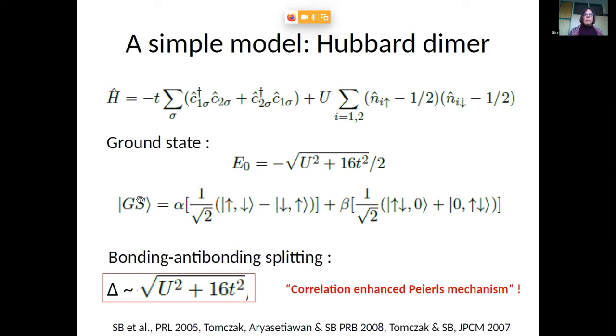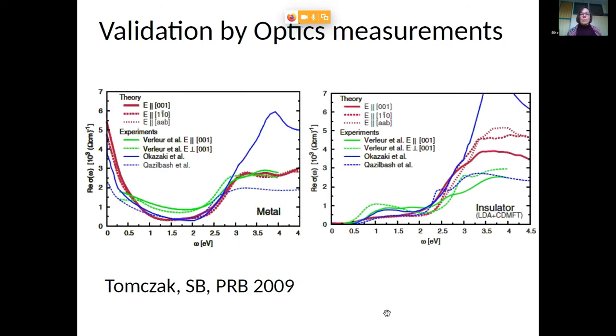And we have the ground state, we have the ground state energy, and we can calculate the bonding, anti-bonding splitting. And there is something interesting, namely this is square root of U squared plus 16 t squared. t is the hopping, U is the Coulomb interaction. If we take the parameters that represent indeed the A1g vanadium dimer in the solid, we find that t is of the order of a fraction of an electron volt, where U is several electron volts, meaning that this energy scale is largely dominated by U. So you do have a bonding-antibonding splitting, but the energy scale of the splitting is essentially set by the Coulomb interactions. And so this was the reason why we dubbed this mechanism a correlation-enhanced Peierls mechanism, because really the energy scales are not the ones of a pure Peierls transition where you would expect the t.